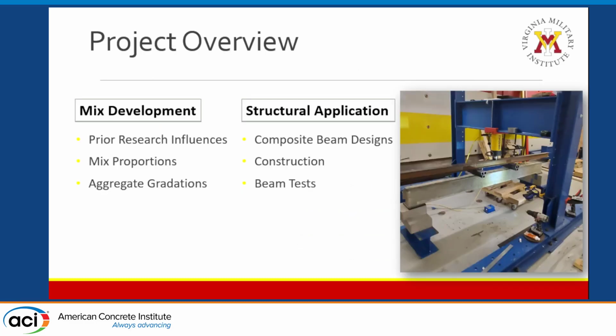This is a joint project completed at the Virginia Military Institute, or VMI, as we'll refer to it from here on out. This project was completed in two phases. I handled the first phase, the mix development of the high-strength fiber-reinforced concrete. The point of my portion of the research was attempting to reach a UHPC compressive grade concrete of about 21.7 KSI by varying the aggregate gradations of different mixes, but still using locally sourced materials.